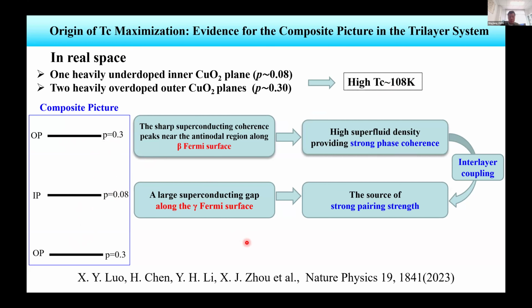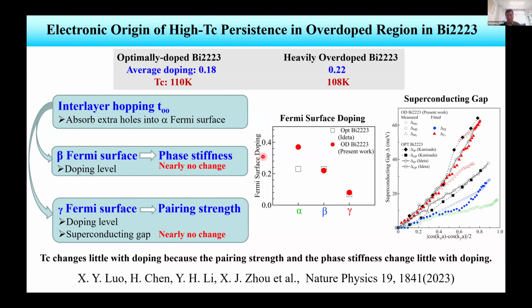Okay, and this picture can also explain why TC does not change much in the overdoped region. If we compare the optimally doped Bi2223 and the heavily overdoped 223, the average doping level goes from 0.18 in the optimally doped sample, where TC is 110 Kelvin, to 0.22 in our heavily overdoped sample, where TC is 108 Kelvin. If we look at the Fermi surfaces, we have three Fermi surface sheets in both the optimally doped and overdoped samples. The extra doping actually goes to the alpha Fermi surface. But for beta and gamma, these two Fermi surface sheets, the doping level does not change much. Also, the gap does not change much for beta and gamma. Only the alpha changes more obviously with doping.